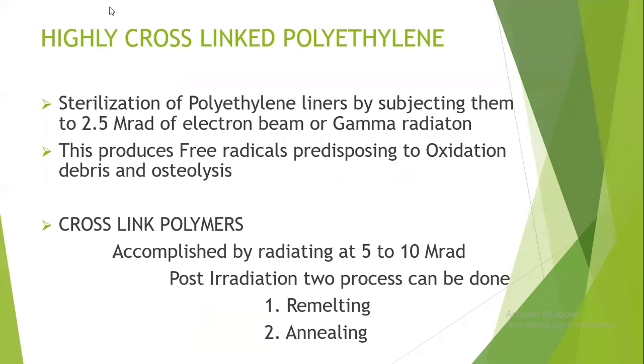Highly cross-linked polyethylene. This involves sterilization. Normally, the polyethylene liners are sterilized with 2.5 megarads of electron beam and gamma radiation. But these cross-linked polymers are achieved by irradiating to higher degrees, up to 5 to 10 megarads. After irradiation, post-irradiation treatment is done by two processes: remelting and annealing.